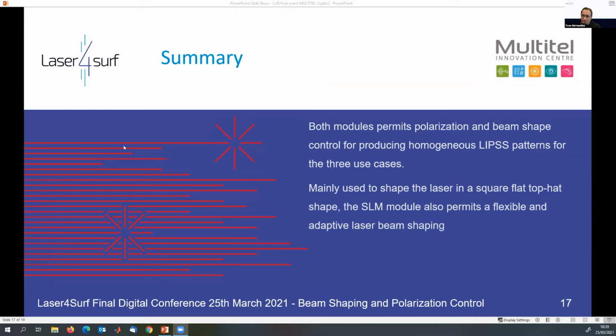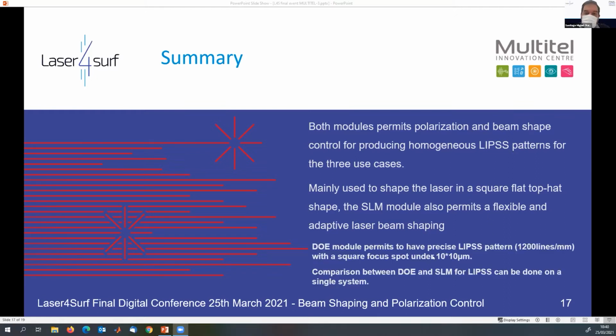So we developed the two modules, polarization and beam shaping, based on DOE and on the SLM solutions. Both systems permit to get flat top shape. With the SLM, it's even possible to do other beam shapes. Both systems are installed at Lasea on Lasea machine. There will be a presentation later on by Lasea explaining all the results obtained with these modules. With the DOE, we can have precise LIPSS patterns with 1,200 lines per millimeter, with a focus spot of 10 micron, which is very important for the encoder application. And the comparison between DOE and SLM can be done on a single system, which is very important with the system at Lasea now.